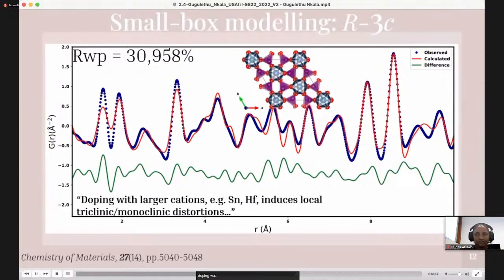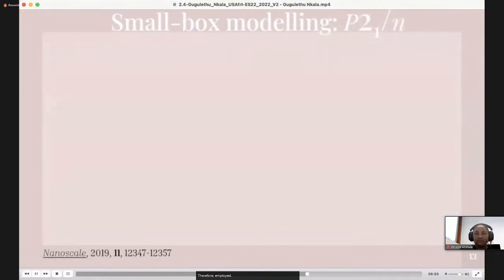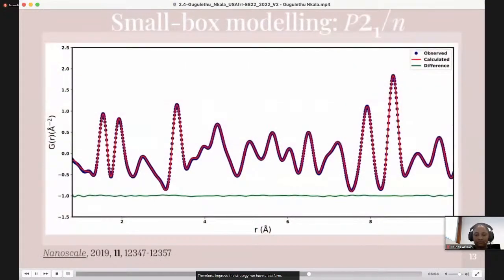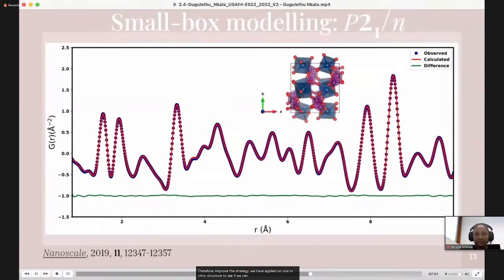Doping with larger cations such as tin, hafnium, and larger M3+ cations has been reported from DFT calculations to induce local triclinic and monoclinic distortions. However, this has not been shown from experiment. Therefore, employing this strategy, we have applied a monoclinic structure to see if we can describe our local structure. And indeed, we do find that at low R, in the region 1 to 10 angstroms, our data is best described using the monoclinic P21/n model analogous to the beta iron sulfate.